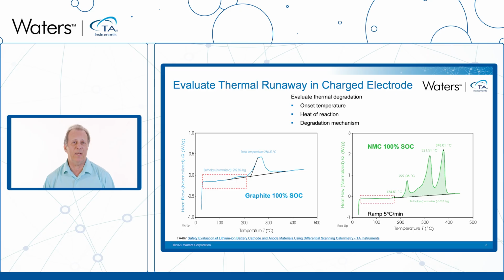The battery was taken apart inside of a glove box, and then the materials, the graphite and the NMC, were scraped off of their respective metal foils, washed with a solution to remove any electrolyte that was still left on them, and then sealed into the high pressure capsules. And then they were run in the DSC.